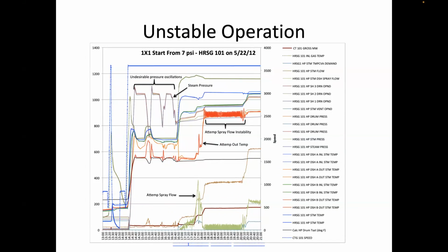This is unstable operation. This can be caused by wear in the control valve, where it's so worn it's not able to control the flow. It can also be caused by sticking of the control valve or sticking in the actuator for the control valve. It could also be a loop tuning problem, but the result is very rapid changes in temperature and a lot of rapid control valve movement, the green line here, which will wear the valve out even faster.